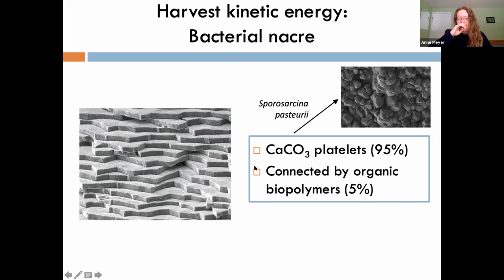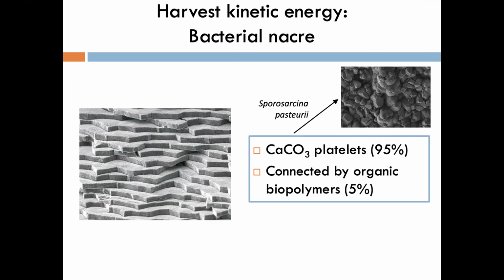Yeah, so there's a bacteria found in the wild that is incredibly useful for our purposes, because if you grow the bacteria in your beaker and give it some urea, it'll break the urea down and raise the pH, and that ends up promoting crystallization of calcium carbonate. So here's a picture of a layer of cement we were able to make in our beaker, where it's only just bacteria and urea and some calcium to make the calcium carbonate with.